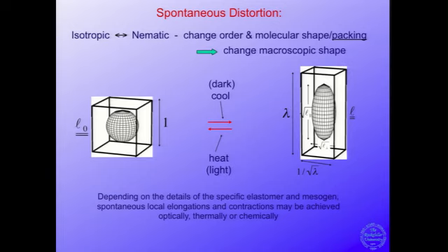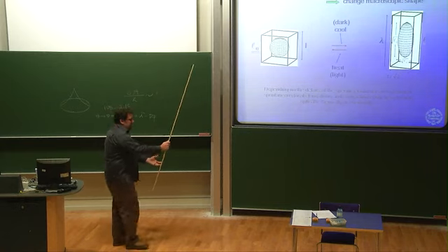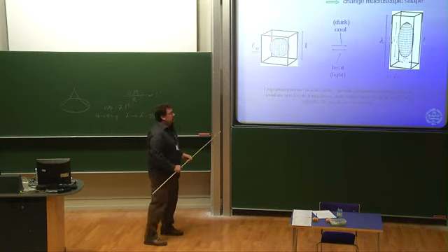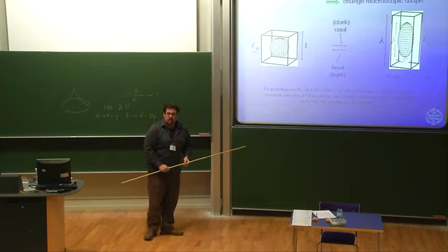A nematic solid is a polymer system that has nematic mesogens on the side chains or possibly on the main chains. The random walk statistics of the polymer change from typically spherical, but when you move into the nematic phase, the random walk aligns preferentially along the direction of the director field, and you can get length changes that are coupled to the strength of the order parameter.